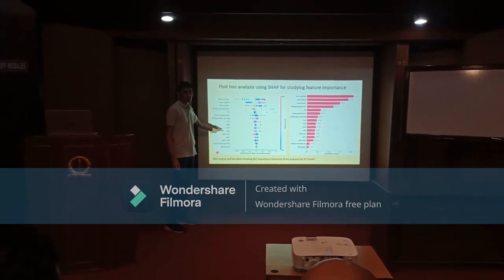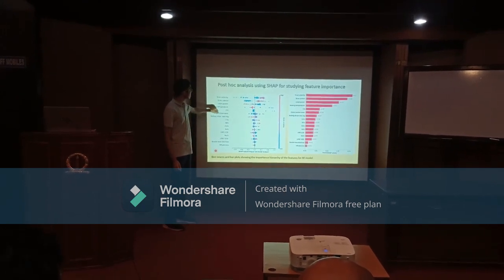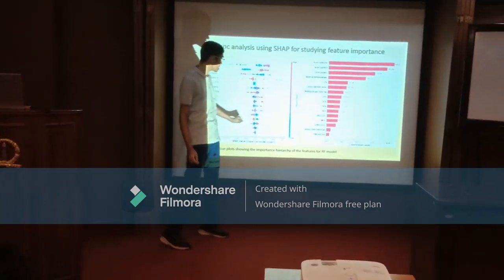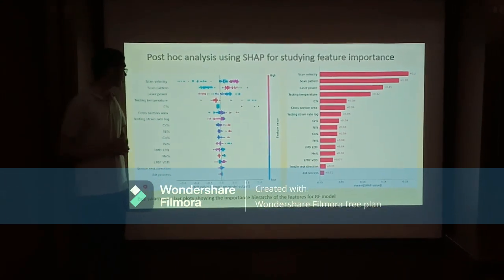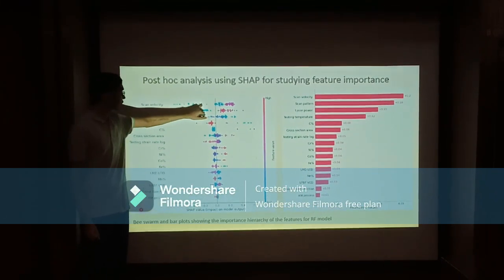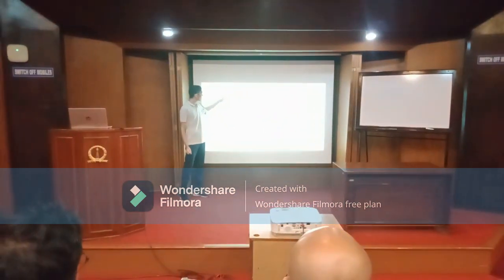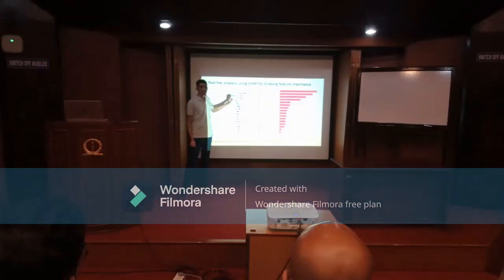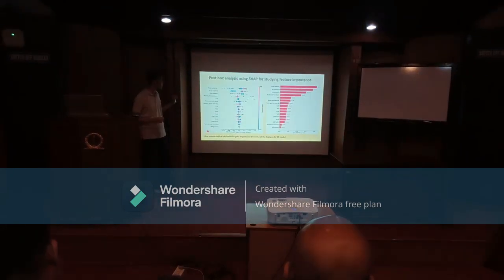In these two plots, you can see that there are different parameters related to the printing process, and the first one is scan velocity. The order of these parameters tells you how much importance the model gave to each parameter. Scan velocity had the highest importance. Also, another piece of information we can get from these plots is these colors. There are light blue colors and darker colors. The light blue colors mean that the feature had a very low value for that particular data point. The darker colors mean that the feature had a much higher value for that data point. Here we can see that the lighter colors are on the left side, on the negative x-axis, while the darker ones are on the positive x-axis.